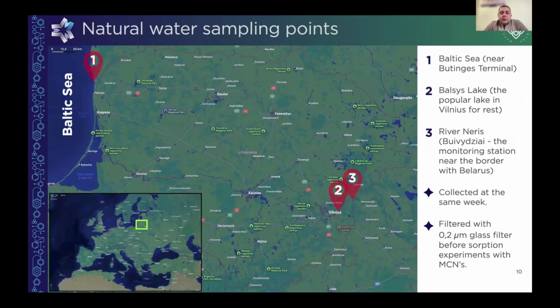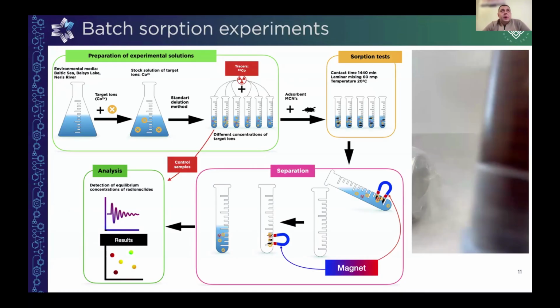And then we used different samples from different points, like the Baltic Sea, Neris River, and Balsis Lake, to study our sorbent's ability to collect the heavy metal cobalt, and here are the points where they were taken. After that, we filtered them through a 0.2 micrometer filter to remove organisms or huge particles that could have a strong effect on the sorbent. And after that, we added a known amount of cobalt ions,